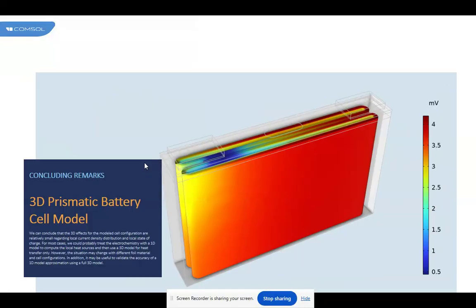And the concluding remarks: three-dimensional prismatic battery cell model. We can conclude that the three-dimensional effects for the model cell configuration are relatively small regarding local current density distribution and local state of charge. For most cases, we could probably treat the electrochemistry with a one-dimensional model to compute the local heat sources and then use a three-dimensional model for heat transfer only. However, the situation may change with different foil material and cell configuration. In addition, it may be useful to validate the accuracy of a one-dimensional model approximation using a full-dimensional model.